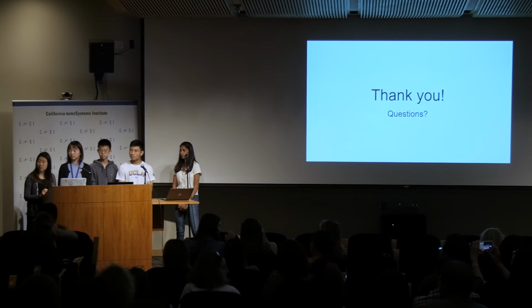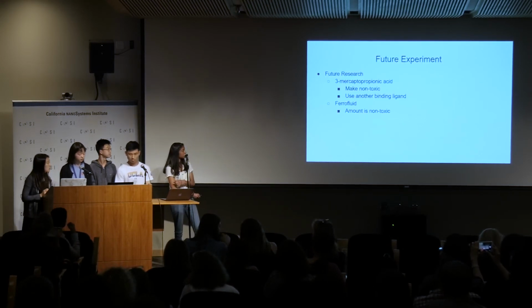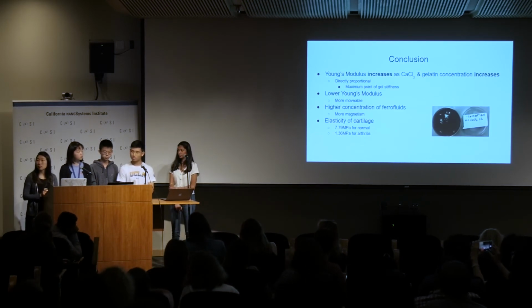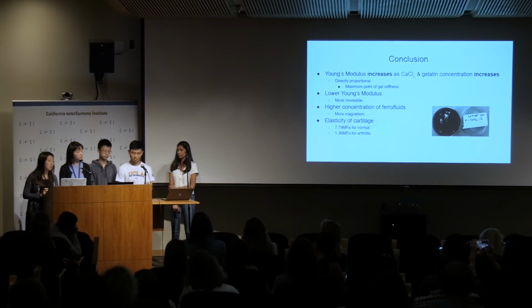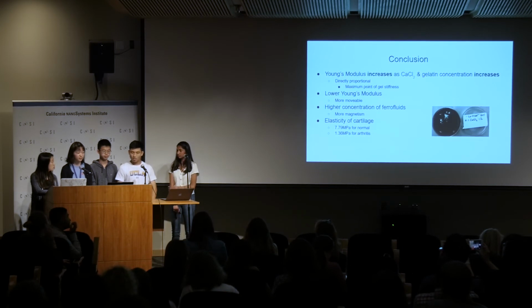All right, I have a question. You did mention at the end the modulus, or the elasticity, for cartilage. How does that actually compare to the data that you got, and how would you further refine your material to match what you're looking for in this application of cartilage in the knee? So in our experiment, we also calculated the Young's modulus. The normal elasticity of cartilage is 7.79 MPa, so we need to make our gels have a similar Young's modulus. From our experiment, the iota carrageenan with 0.3% calcium chloride would be the closest to the Young's modulus for cartilage.